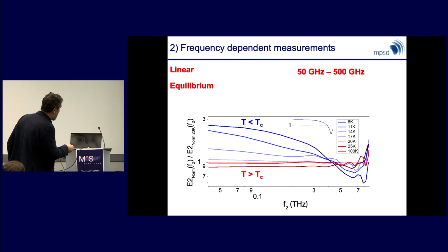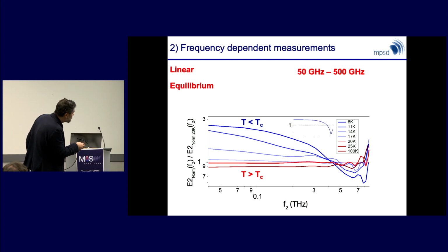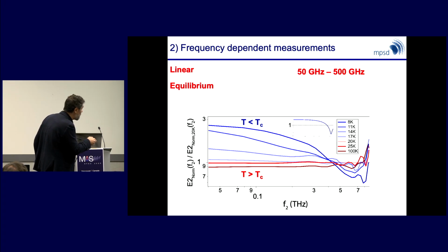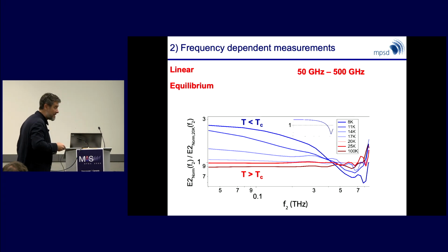Remember, compared to the optical measurements, what's great about these experiments is that they allow me to probe at frequency scales between 500 gigahertz and less than 50 gigahertz. Above 500 gigahertz, you start having resonances of the circuit, so things get a little harder. But this is a simulation of what you would expect. Here, there's some LC coupling that gives you a resonance.